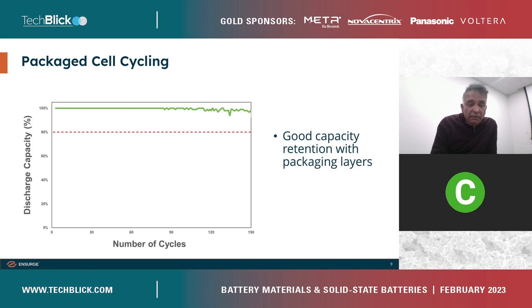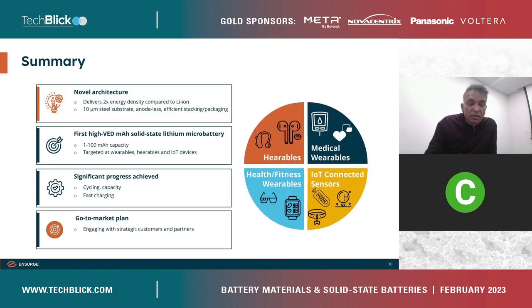What we have not shown here is the unpackaged cells cycling. We have, of course, taken those also to hundreds of cycles, and it does not take a whole lot of moisture, even inside a glove box, to reduce the CE from 99.9 to 99.5. So it is very important that the overall packaging is in place and acts as a good encapsulant with good mechanical properties as well. That's a quick look at the data about our cell in this very quick talk.